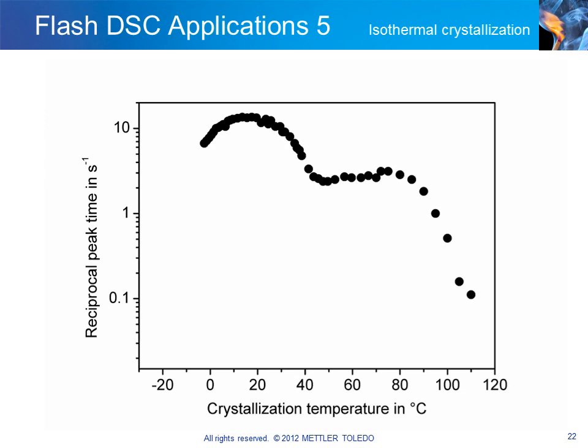This diagram summarizes all the measurement results. The reciprocal peak time at the peak maximum of the measurement curve is displayed as a function of the crystallization temperature. The reciprocal peak time is a measure of the crystallization rate. Two different crystallization processes are apparent. The heterogeneous crystallization below 40 degrees is faster than the crystallization at higher temperatures.